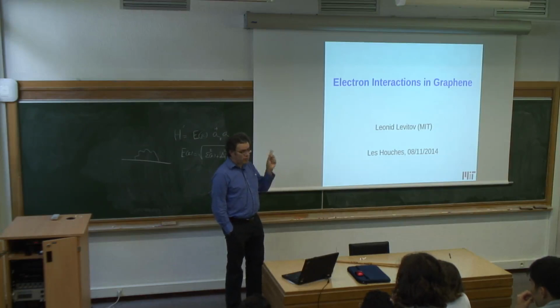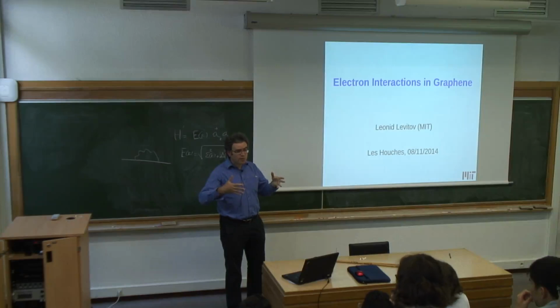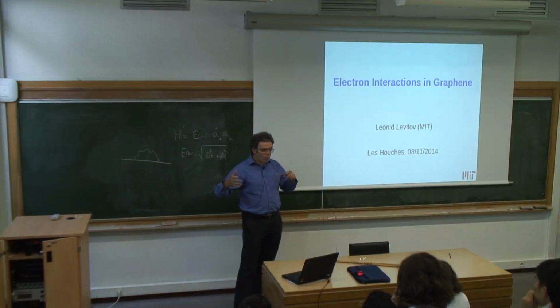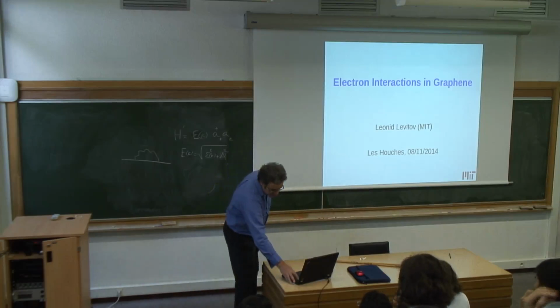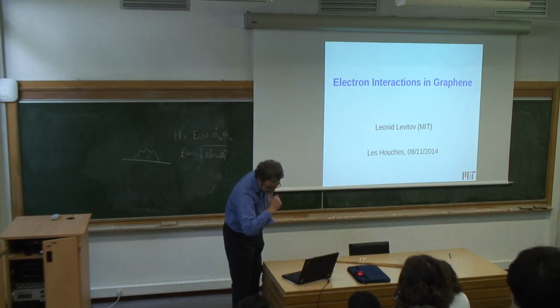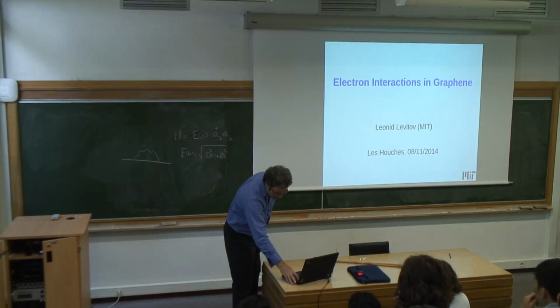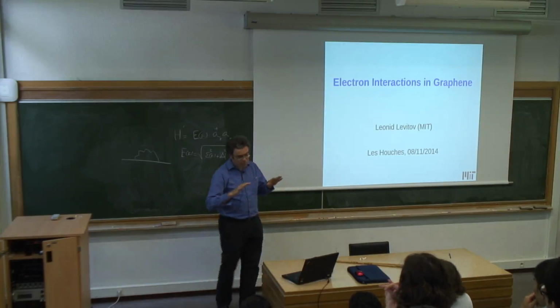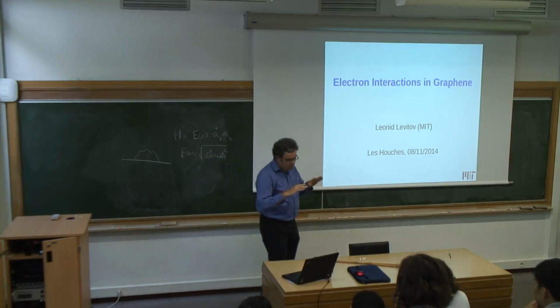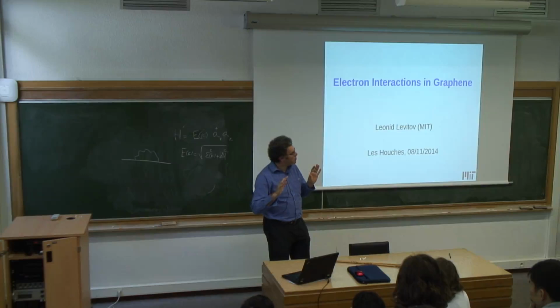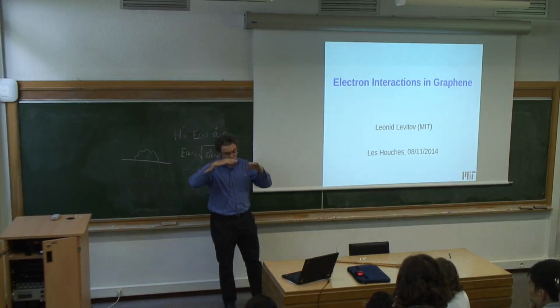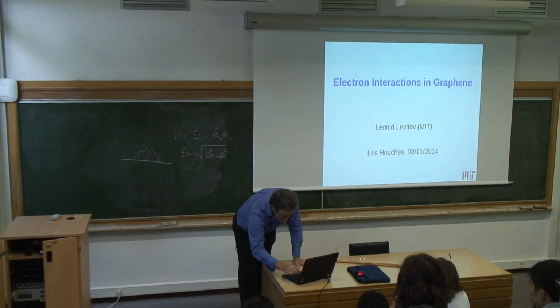One can either try what we discussed, to place graphene in some polar environment, and then there'll be some strong polar phonons in the environment, and electrons in graphene will be coupled to these phonons. Or one can follow a different route, and that's in this paper that we wrote 3 years ago, where you use pure Coulomb interaction effects, no phonons. But for that you need to dope graphene heavily to the point where you reach saddle points in the graphene band structure. Maybe I'll just show you one slide. How do I do this?